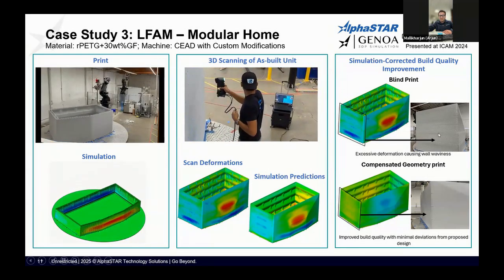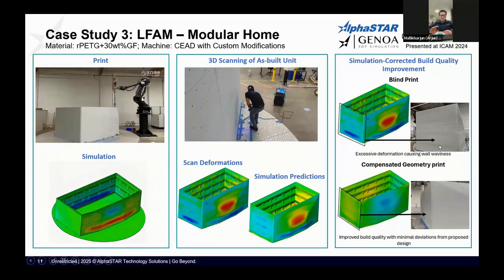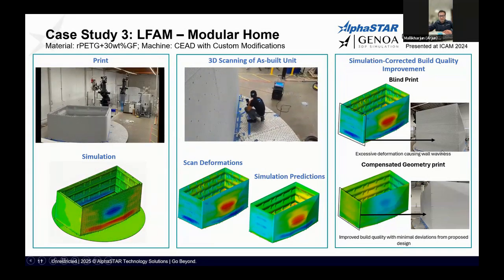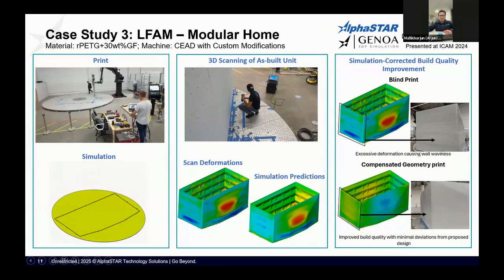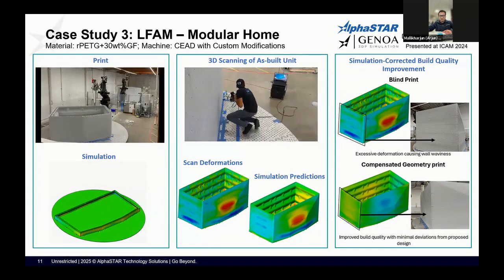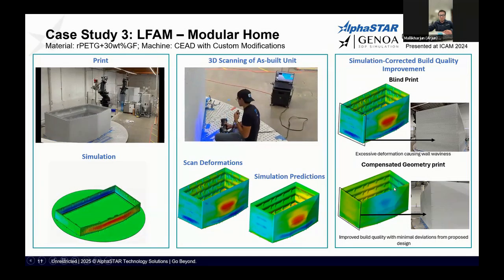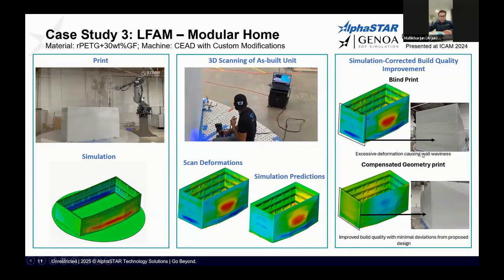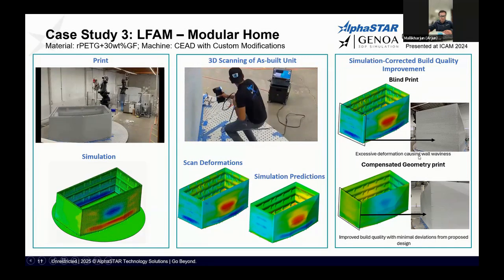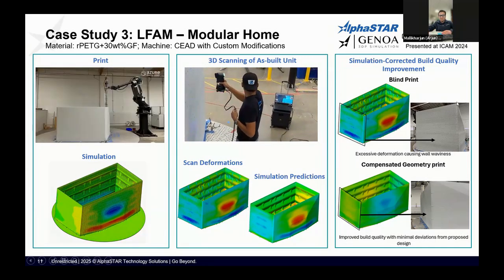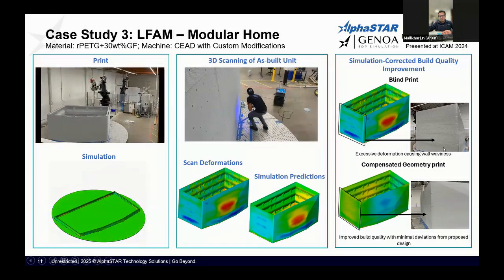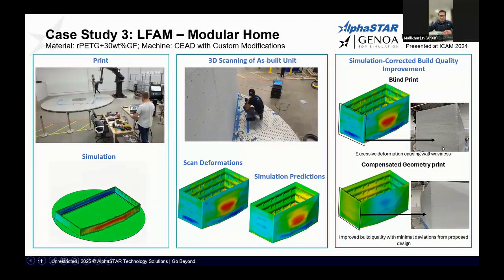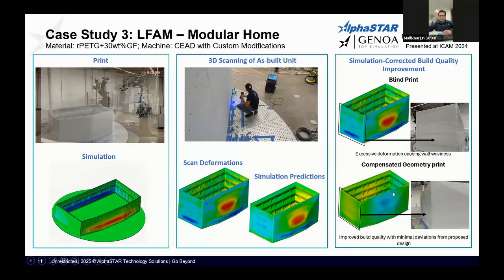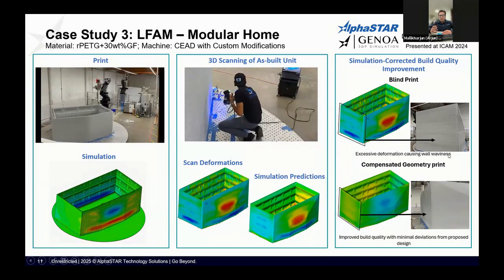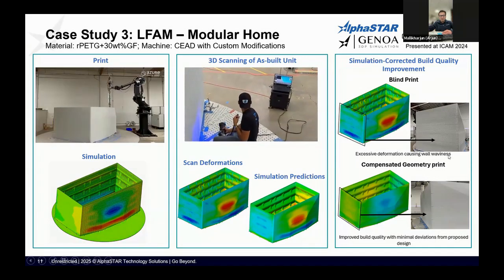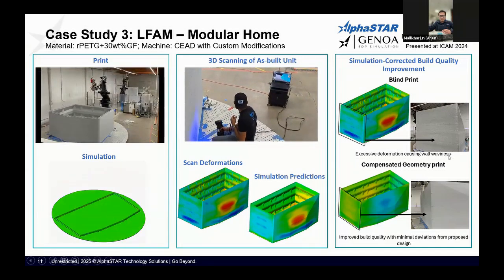With that, we moved on to the next step of, okay, now the simulation is able to predict everything perfectly. How about compensating it and seeing if compensation is able to solve a lot of these issues? That's the validation on the rightmost pillar, where the blind print, which is no simulation, just getting the GCode printed, where you can see one side of the wall here, which is extremely wavy. And because the structure is gigantic, when we say wavy, here we are talking about 10, 20 millimeters in and out. So you can visually see it when you look at the structure.